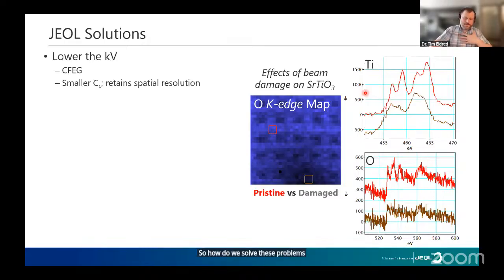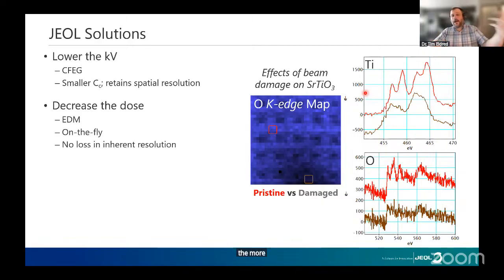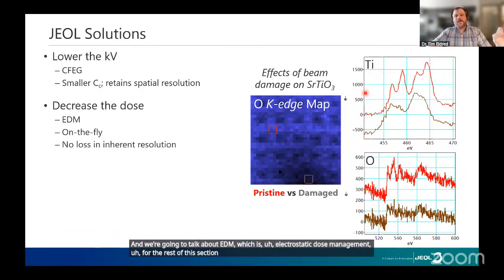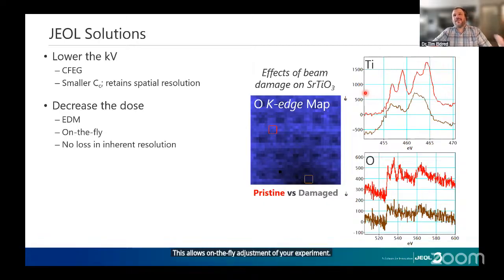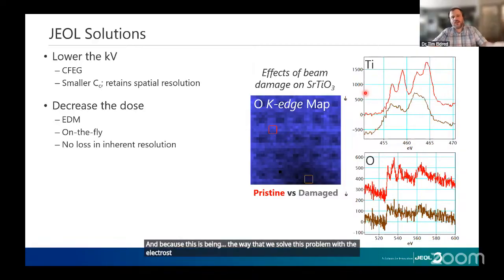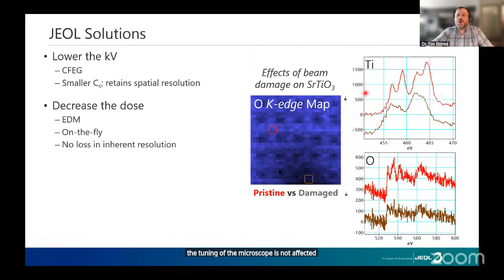So how do we solve these problems? Well, when you lower the kV, you have a tendency to increase your aberrations, which makes atomic resolution more difficult, because you have more chromatic aberrations at that lower potential. We have cold FEG guns, which allow us to maintain a very tight energy distribution, even at the lower potentials. This allows us to retain the spatial resolution. The method that I tend to favor is just decreasing the dose. And we're going to talk about EDM, which is electrostatic dose management, for the rest of this section. This allows on-the-fly adjustment of your experiment. And because we solve this problem with the electrostatic shutter, the tuning of the microscope is not affected. There's no loss in your resolution. The rest of the microscope is still the same. There's no change in your energy.